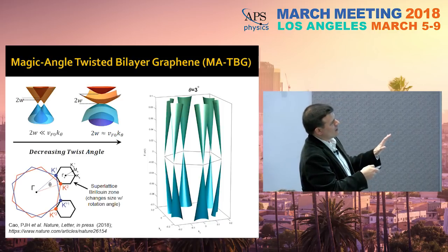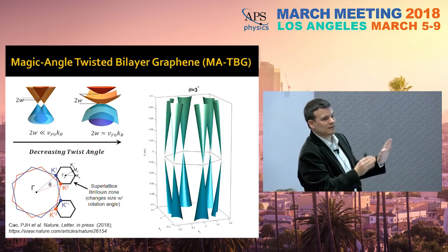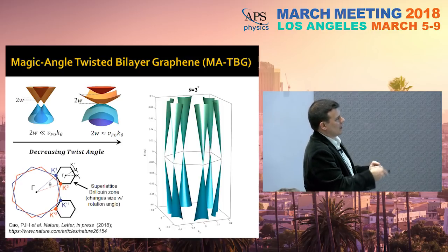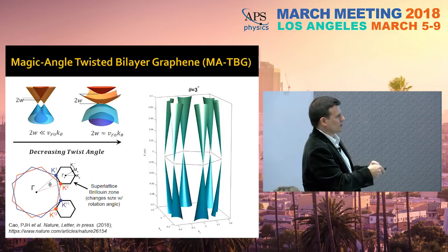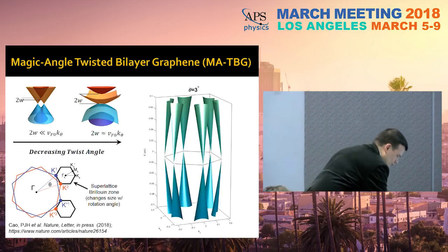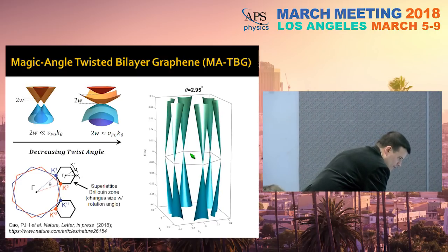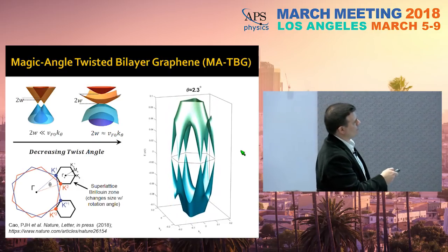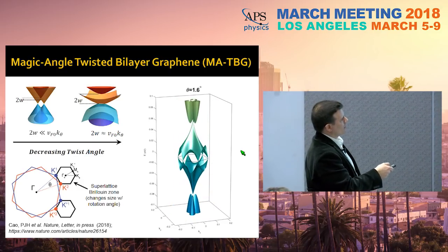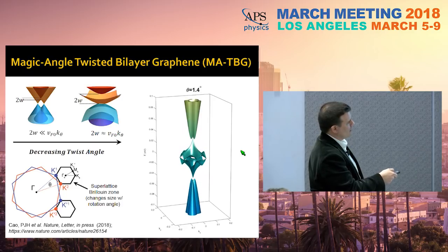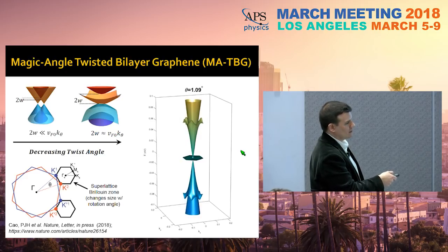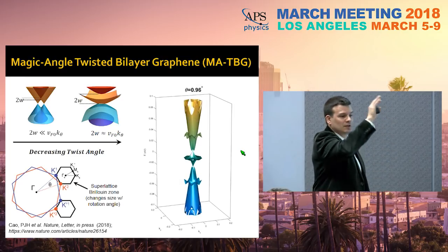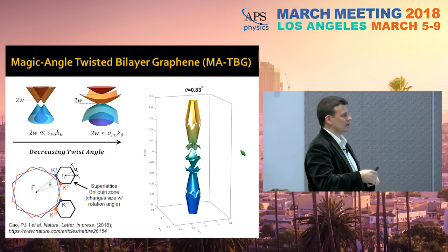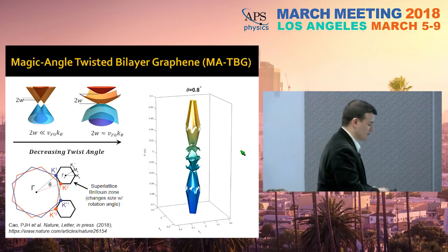As you can see, if you are at 3 degrees, which is a relatively large twist angle, what you see are Dirac cones stemming from the corners of the superlattice Brillouin zone. So let me show you now what happens when you twist the angle. As you see, the band structure is evolving. As we get towards lower and lower angles, this starts becoming very small bandwidth, and you're going to see a total flattening there at 1.1, a flat pancake. If you keep decreasing, it evolves again. And actually, it keeps going. You can go to a second magic angle, to a third magic angle. It gets very complicated.